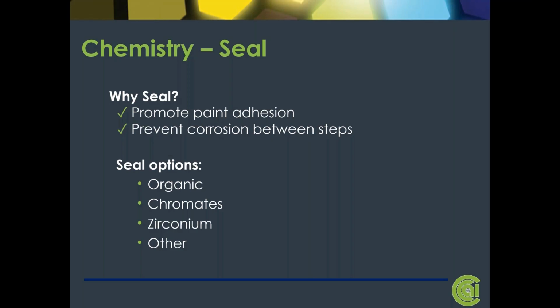Seals are also used at the end of a multi-stage line or after a manual spray line to prevent corrosion going to the next step. Now, these seals can be your typical organic seals such as non-chrome, some quaternary amines, something like this. I've even seen zirconiums used as a seal over iron phosphates, and the use of chromates is still there. It's mandated. Typically, it's going to be military or aerospace, but they are still there, and we need to be aware of those. But those are the reasons you would use a seal at the end of the line.